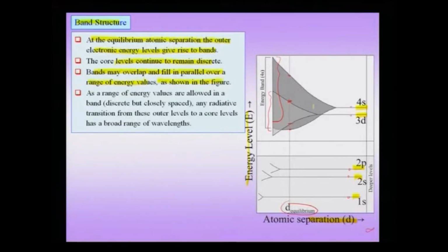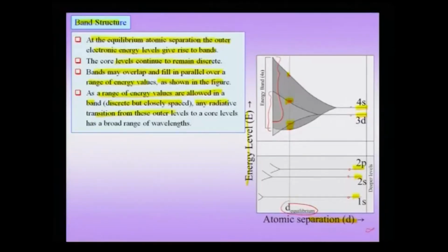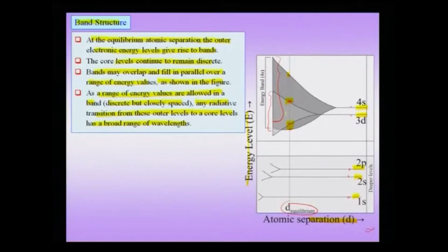That means that once I am in the energy region between here and here, I am going to be filling my 3D and 4s bands parallelly. As a range of energy values are allowed in a band, and of course, we know from Pauli's exclusion principle that they are discrete, but they are closely spaced. Any radiative transition from these outer levels to a core level has a broad range of wavelengths. Because if you look at an atomic emission or absorption spectrum, that will tend to be very sharp. But suppose you have a radiative transition from these bands, they will have a continuous energy value, because these bands themselves have a continuous range of energy levels.